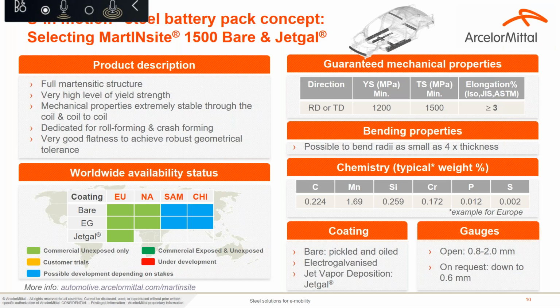Jetgal, in fact, is technically, for the customer, equivalent in properties to an electro-galvanized coating, but presents different advantages, which can be discussed in a separate discussion. Regarding the coating, we can also deliver, as I mentioned, electro-galvanized, Jetgal, and also bare. And regarding the gauges, we can deliver from 0.8 to 2.0 millimeters, which covers all the needs. And on request, we can go down to 0.6 millimeters.